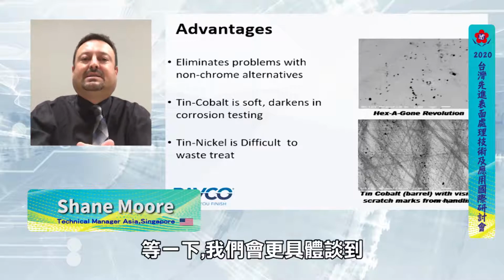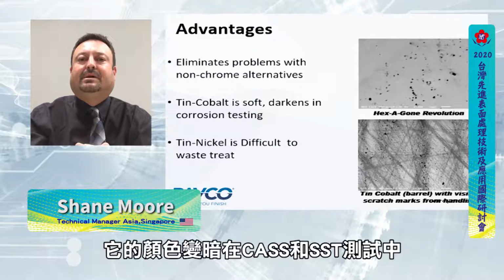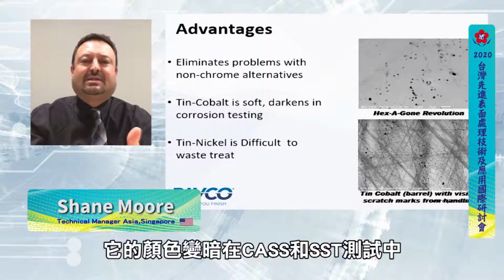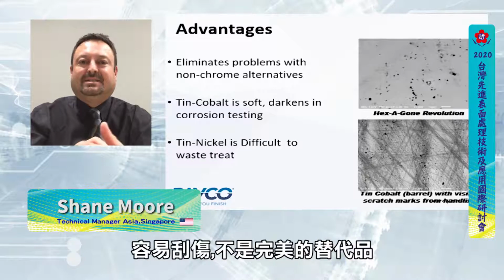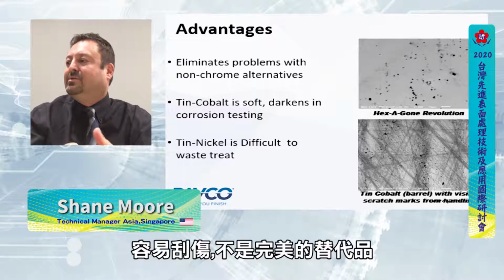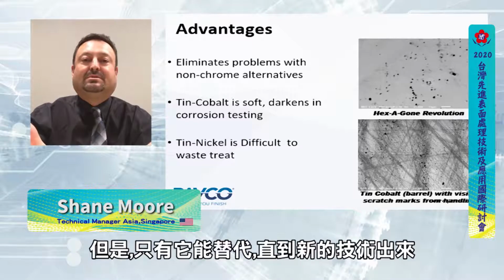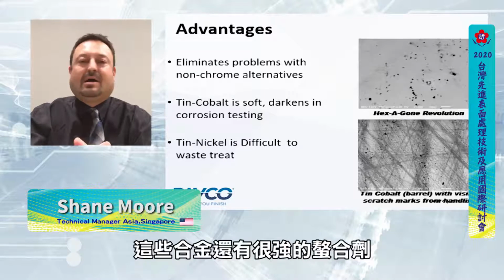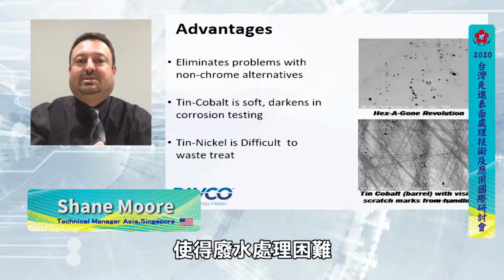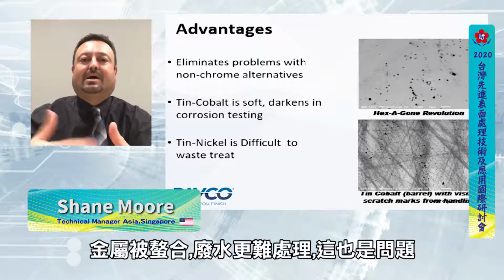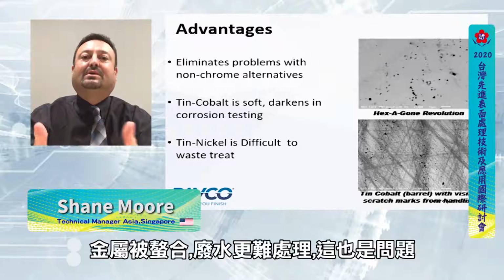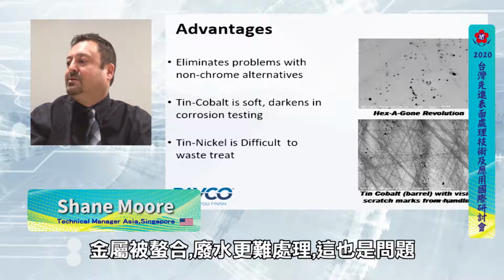We'll talk about this later in more detail, but it seems to darken almost immediately after being exposed in a CASS chamber or neutral salt spray chamber. It's very soft, so it's easy to scratch. So it's not really a good alternative. But of course, that was the only thing that was available until this new technology. So some of these other alloys have strong chelators, which makes it much harder to waste treat because it likes to chelate the metals that you're trying to precipitate from your waste treatment effluent. So we have problems there too.